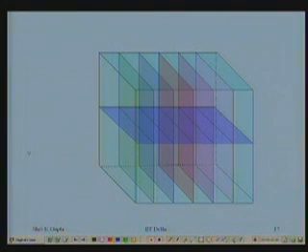Problem arises when one of these planes, let us say in the middle, this one, below this horizontal plane here, does not have this part, no atoms are placed here. When no atoms are placed in this area, what would happen? The atoms which are placed in the neighboring planes become too far, they will try to come closer because they will like to form bonds, and they come together because the atoms in this plane are missing. This plane I call an incomplete plane. Let us see what happens when I have an incomplete plane.